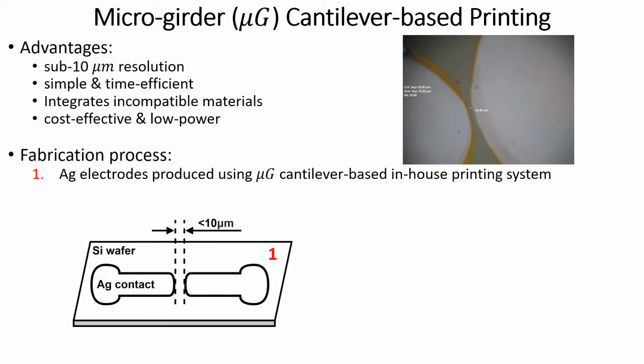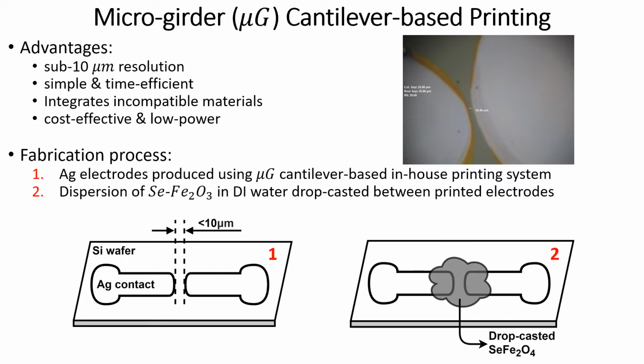The fabrication process occurs in a two-step process. In the first step, we produce the silver electrodes using our in-house printing system. In the next step, we drop cast the dispersion of the material used for the device in deionized water.